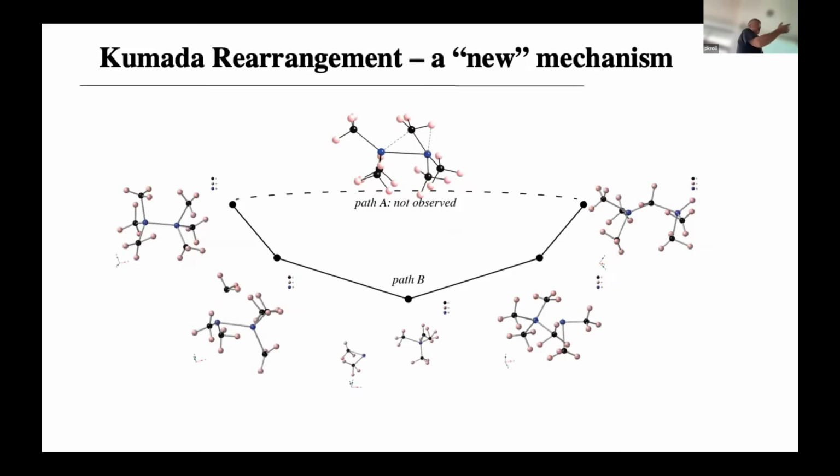So this is 65-year-old stuff. We have the bis-trimethylsilane, or whatever you call this, or disilane, yes? So silicon with the 3 methyl groups. You start with a gas of this, and in the end, in your mass spec, you observe this, where the carbon has inserted between the 2 silicons, and now you have an Si-C-Si bridge.